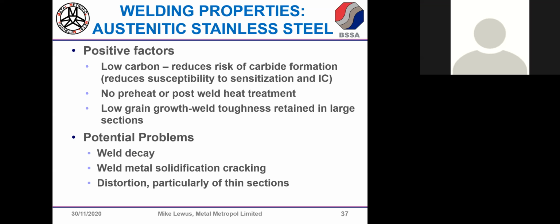Anyhow, welding properties. I'm just going to stick with austenitics. The good thing about austenitics is they're very good to weld. You can readily weld the material in thick sections, unlike ferritics. And unlike martensitics, which are the only heat-treatable family type, we don't have to worry about preheating the material or post-weld heat treatments. So that's a big plus. They're very readily weldable. There is one caveat.